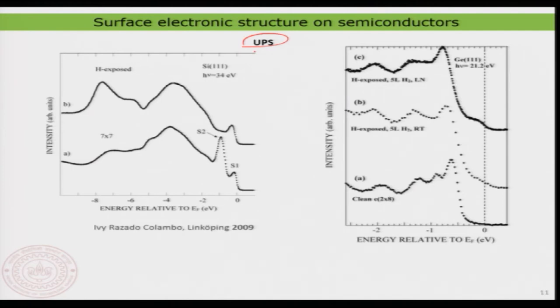What I have here is actually a silicon 7x7 surface. What you are seeing is the same kind of spectrum you have seen in the previous slide, but in a larger window. That means I am looking at deeper and deeper binding energy of electrons, so I am looking deeper into the valence band, for example. Again, you have the S1 and S2. These are the surface states, and then as you go deeper, you start to get the normal states corresponding to the silicon itself.